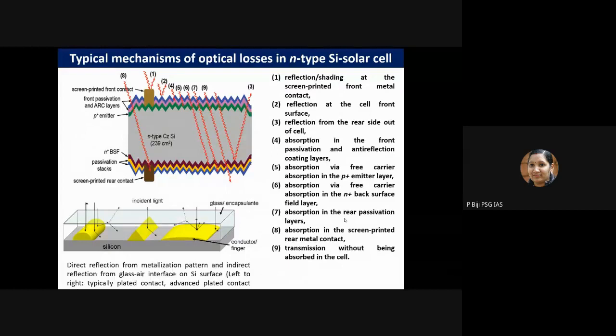The second is the reflection at the cell front surface. Then the third contribution is from the reflection from the rear side out of the cell. Then the absorption in the front passivation and anti-reflection coating layers. Then the fifth contribution will be from absorption via free carrier absorption in the P type emitter layer.